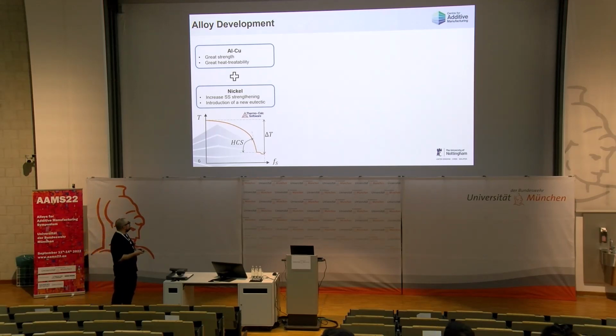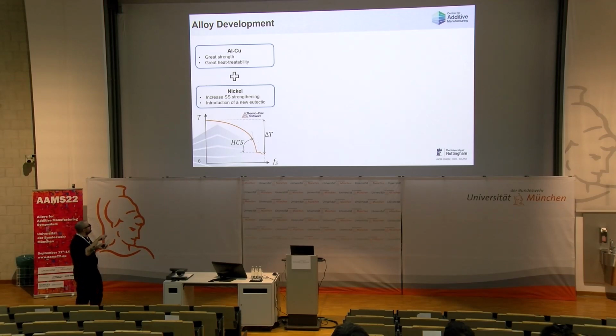And then we compute solidification paths via Thermo-Calc, and we evaluate the HCS, the slope at the end, and the solidification range. Here we also validate the solidification path by investigating the phases present in the microstructure via XRD, so that we know the phases that we put in the solidification path during cooling are the exact phases that we actually found in the microstructure.